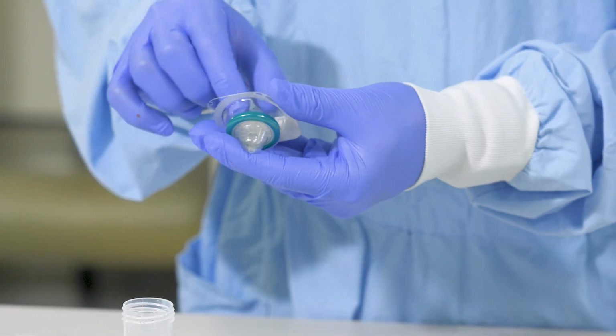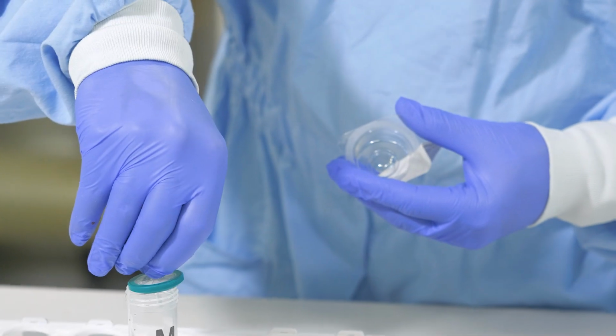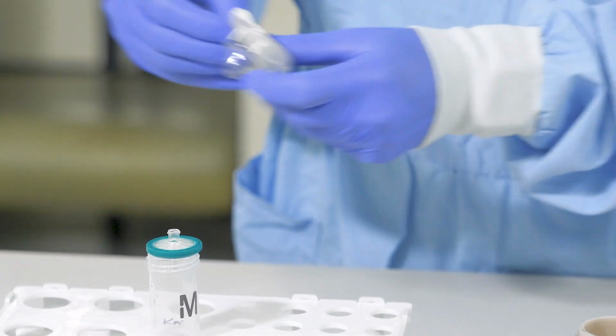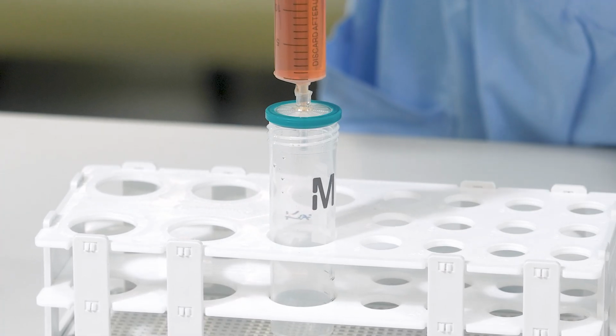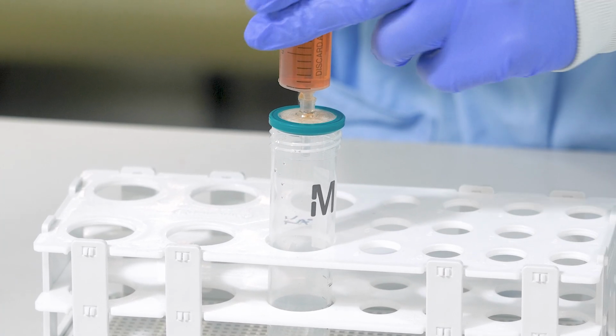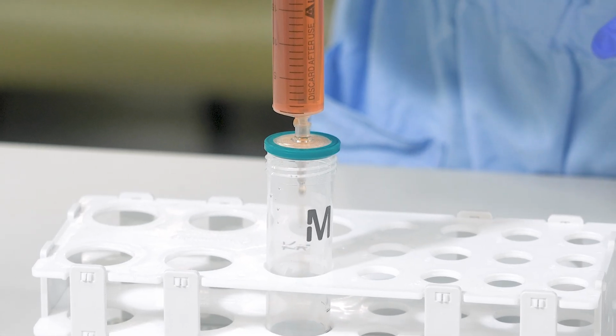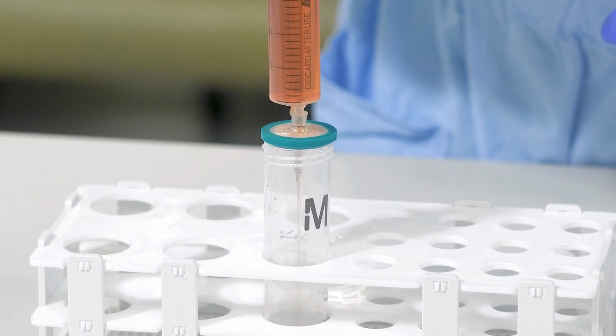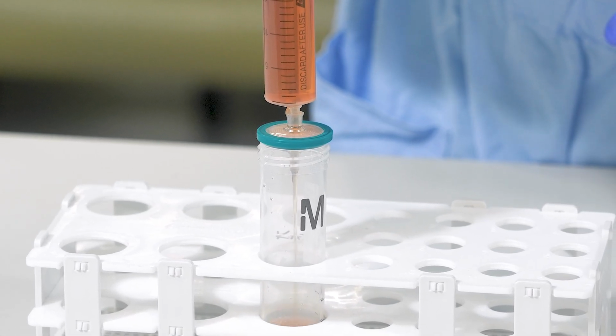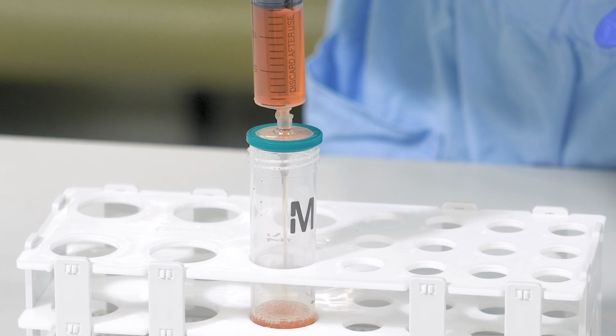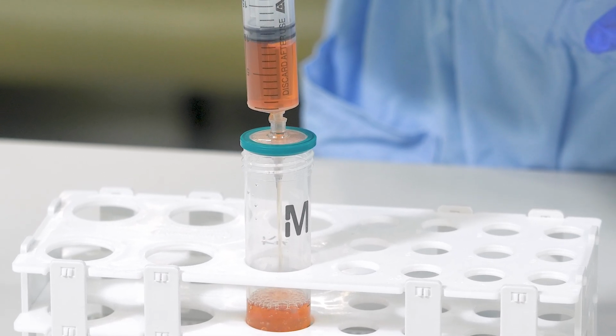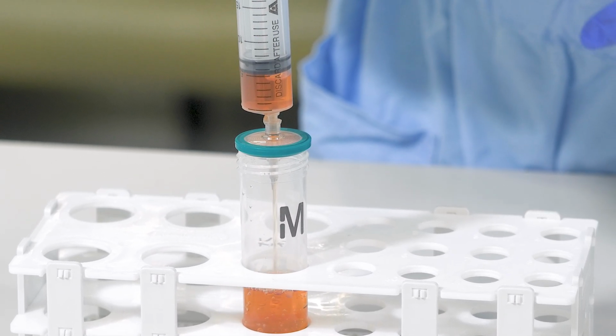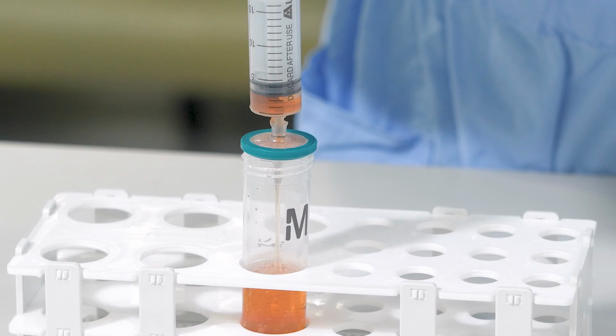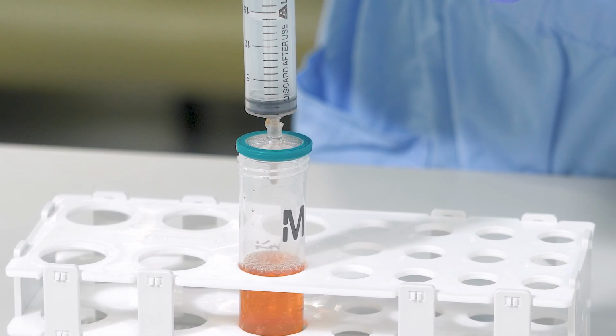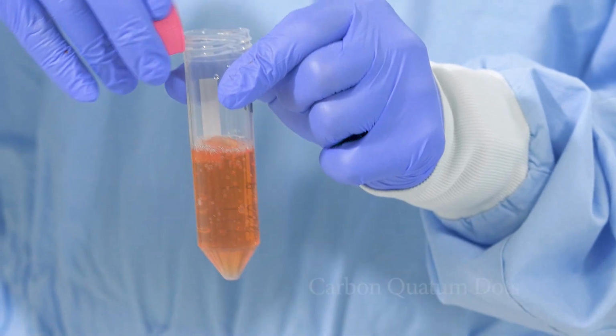Then I attach a 0.22 micrometer filter and push the sample through it with the plunger into the plastic flask over here. It has a volume of 50 milliliter. That should be enough to hold most of our sample. So as you can see, this filter will help us to remove the contamination and the unwanted particles from our solution containing carbon quantum dots. There we have it, pure carbon quantum dots.